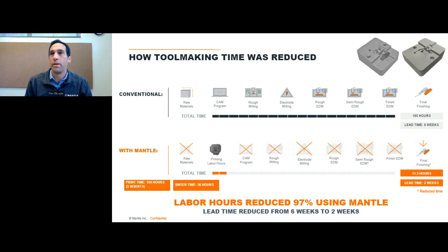But the total toolmaker time went from 180 hours down to 11 and a half hours. And the time to launch and mold the plastic part went from 6 weeks down to 2 weeks. So you're able to get the molded part in the hands of their customers that much more quickly. So that was the value for them, and doing so in a way that was unattended and that didn't tax their toolmakers as much. Like most folks, they have a relatively small toolmaking team, and they're incredibly busy and taxed. And so the ability to increase the throughput through the tool room was of great value to them.